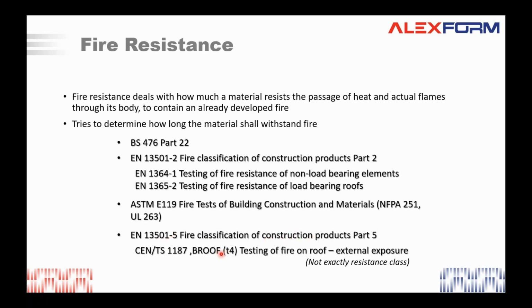For roof, what is required is the top requirement, B roof T4 class. This I put here under fire resistance, but it's not. It's a hybrid test. It includes, again, flame spread measurement, etc., but also measures fire penetration. So the test is run for 60 minutes. At the end of 60 minutes, there should not be any fire penetration. But of course, if it is withstanding the fire a longer time, you will never come to know. So this is not exactly a resistance class, but it's better to include it here.